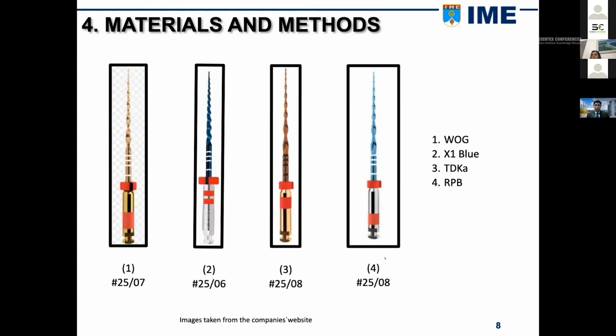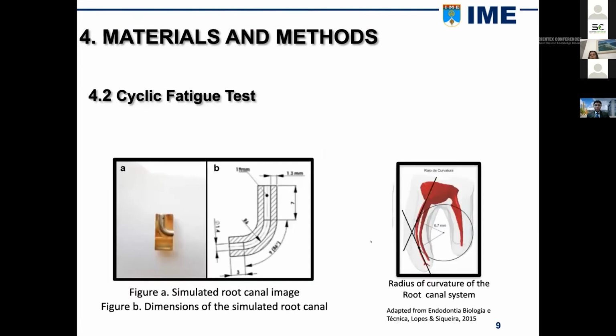This picture shows instruments used in mechanical testing: Wave One Gold, X1 Blue, TDKa, and Reciproc Blue. To evaluate the mechanical behavior, wires and instruments were submitted to rotation fatigue tests. Testing was performed using a simulated stainless steel channel. The wires were tested in continuous rotation at a speed of 500 RPM until fracture. Subsequently, the instruments of each group were tested in reciprocal movement according to the manufacturer's instructions. The instrument is rotated clockwise and counterclockwise within the channel.